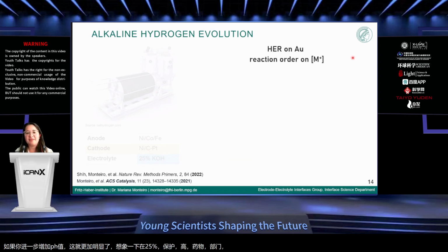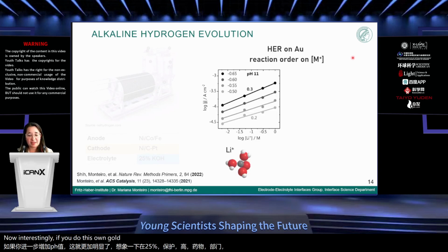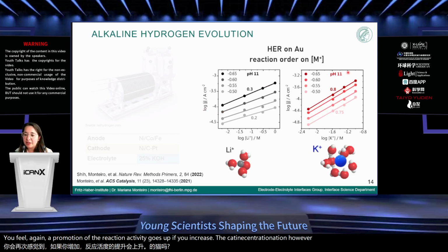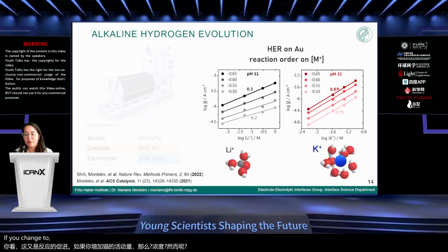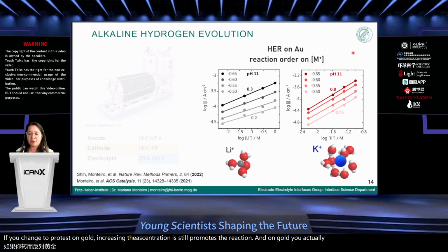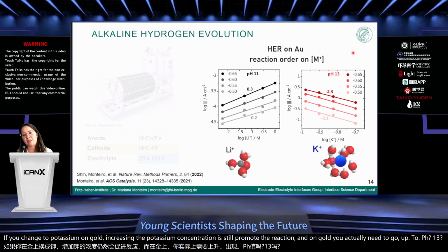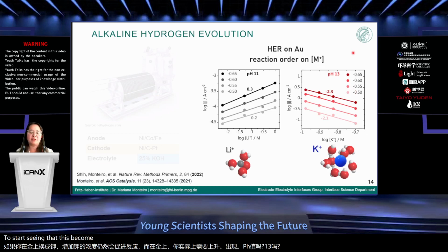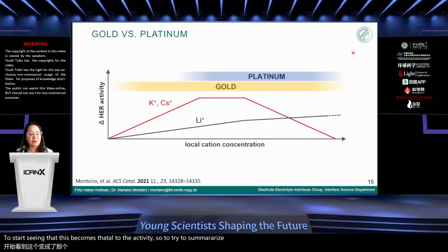Now, interestingly, if you do this on gold, first lithium at pH 11, you see again a promotion of the reaction. The activity goes up if you increase the cation concentration. However, if you change to potassium on gold, increasing the potassium concentration still promotes the reaction. And on gold, you actually need to go up to pH 13 to start seeing that this becomes detrimental to the activity.